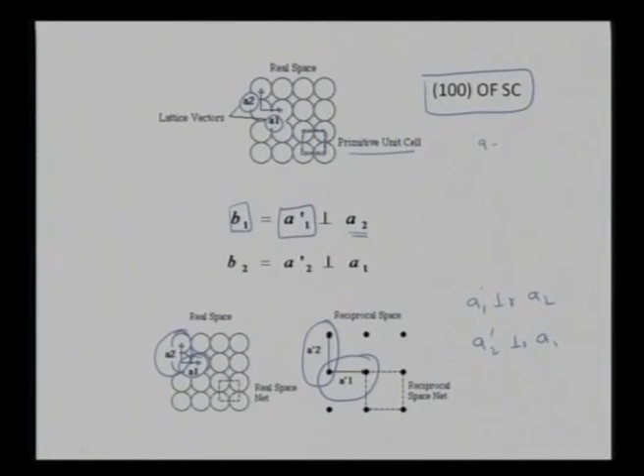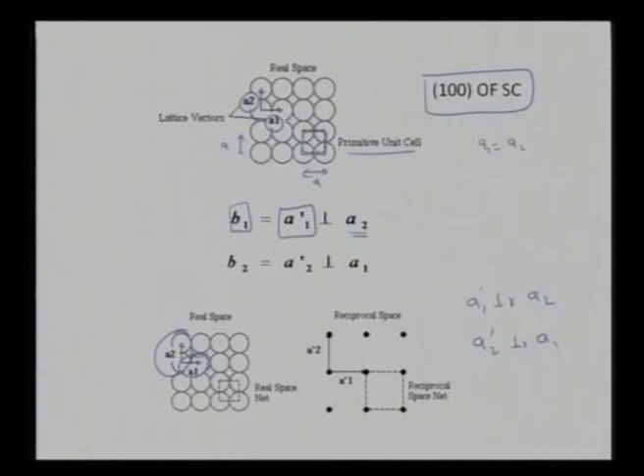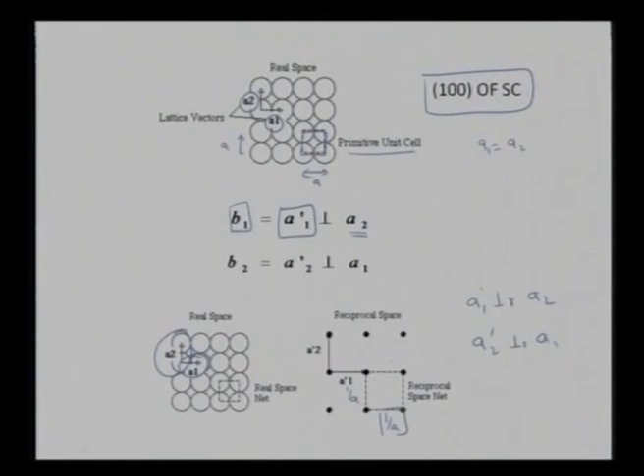At the same time, the distance a₁ is equal to distance a₂. This unit length is a along a₁ and also a along a₂, so a = b. Once I come to the reciprocal lattice, the distances are 1/a₁ and 1/a₂, and since a₁ = a₂, this was a square in real space and remains so in reciprocal space — 1/a is similar along both axes. My a₁' axis is similar to the a₂' axis in terms of magnitude, so it is still forming a square.